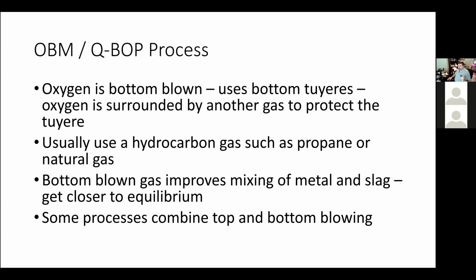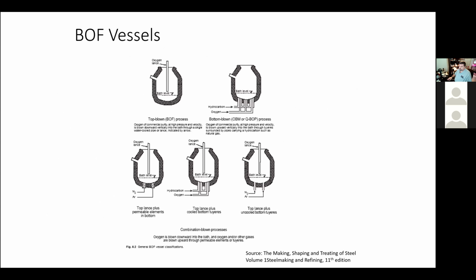There are other variations of the process. There's one called the QBOP, where oxygen is blown into the bottom of the vessel. And we typically shroud the oxygen with natural gas or propane in order to cool it so that it doesn't burn back to the bottom of the vessel. And bottom blowing allows you to move closer to equilibrium between the steel and the slag. And then there are some processes that combine top and bottom blowing. So these are all different variations of the BOF process.